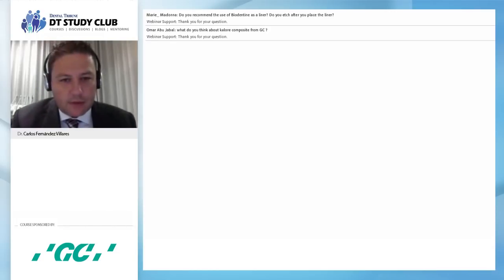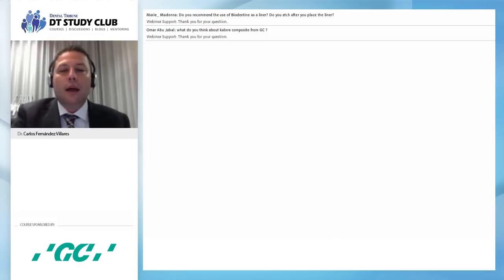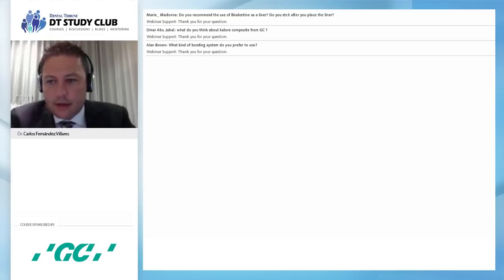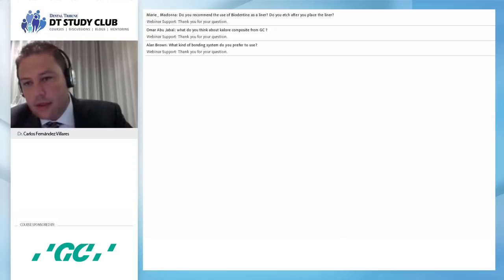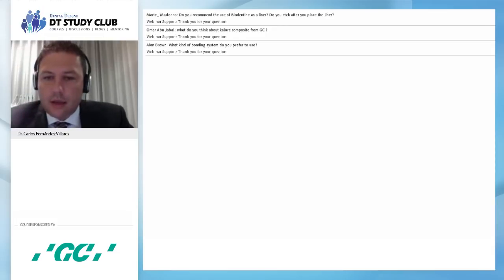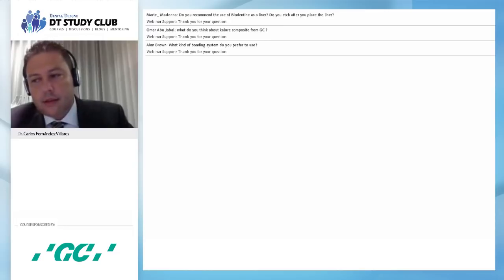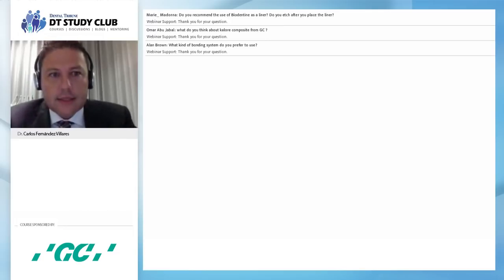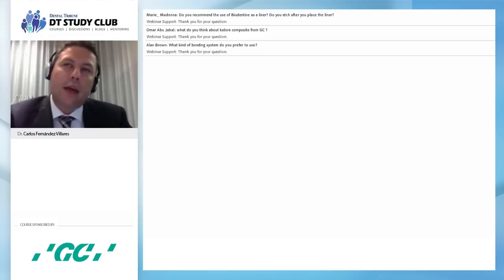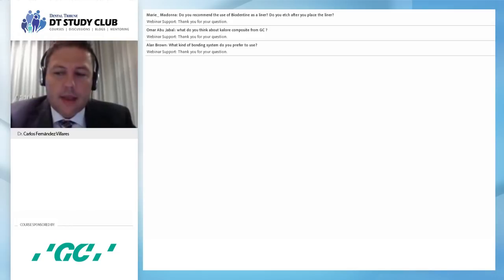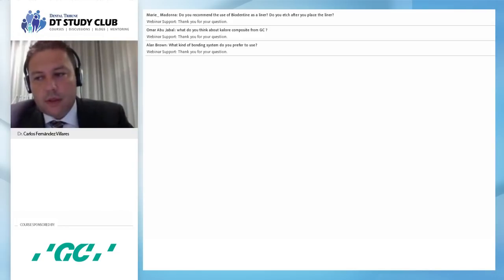Alan Brown asked me what kind of bonding system I prefer to use. I have to say, in posterior, I normally use self-etching systems, but always etch the enamel first because they still don't have enough bond strength in the enamel, but it's very good to avoid etching the dentin with normal etching systems. In anterior, I prefer to use three-step systems, I mean etching and then the primer and the bonding separate.